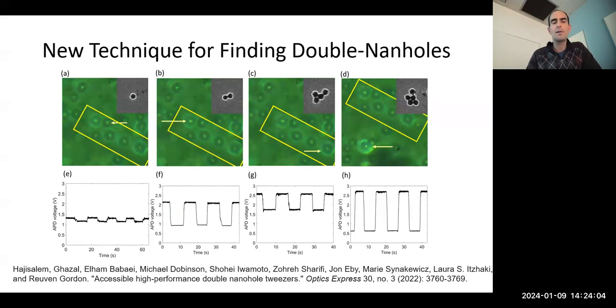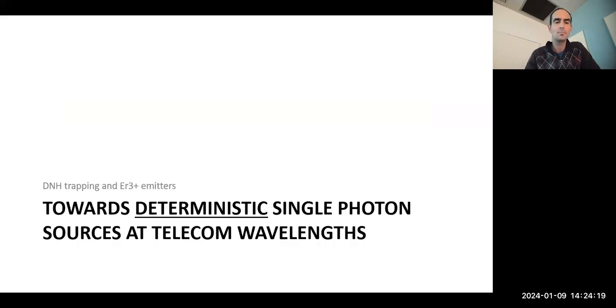Because this is a random process, you get single apertures, double apertures, and clusters of four or more. But we focus in on the doubles, and we know how to identify them by looking at the polarization and optical intensity properties we see in the microscope.